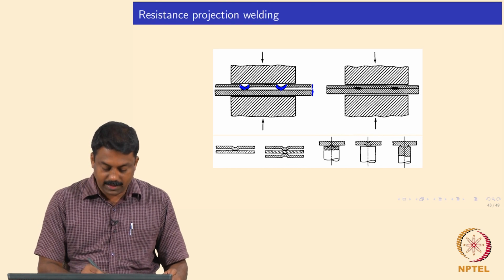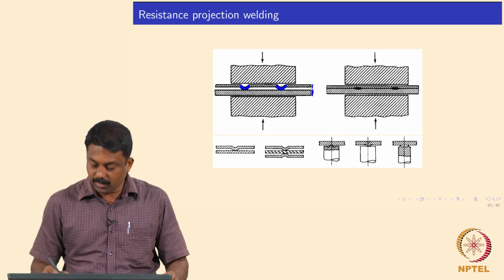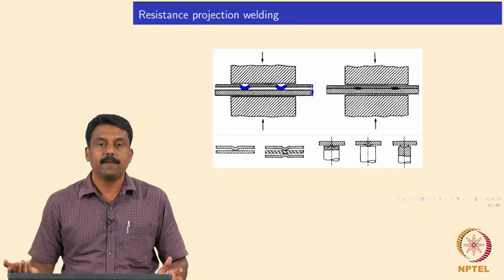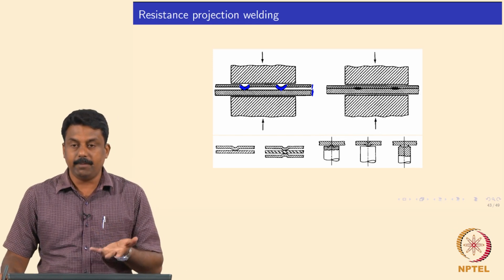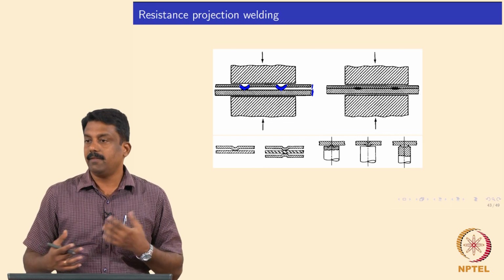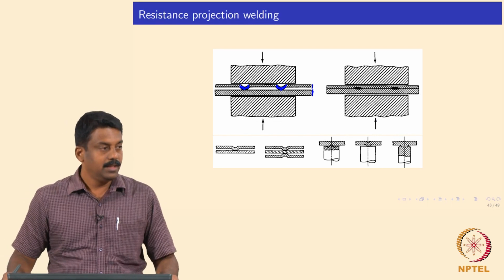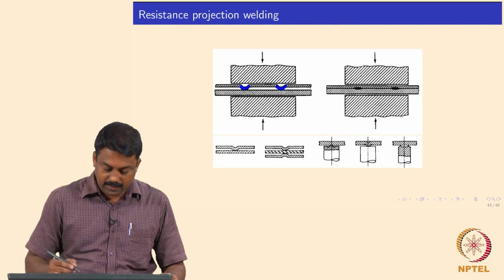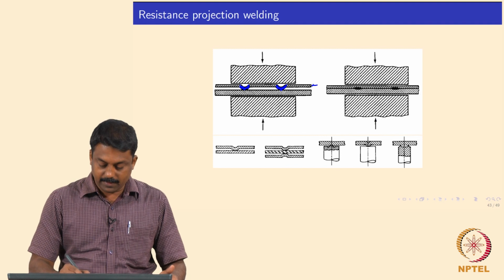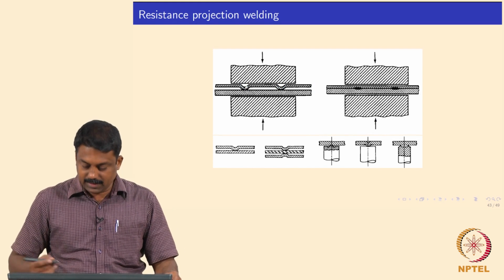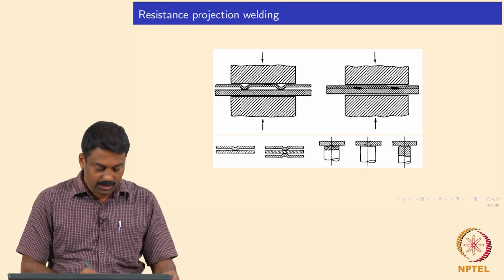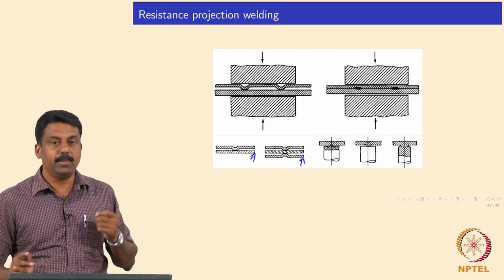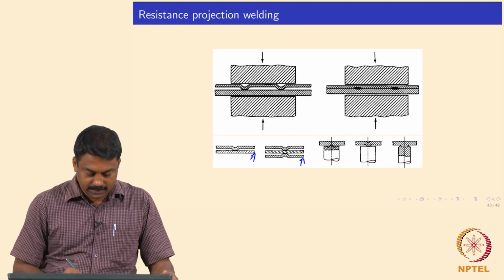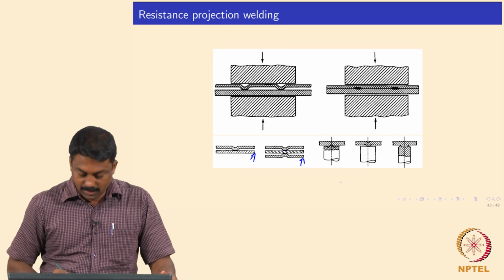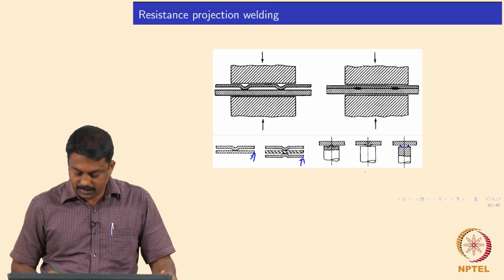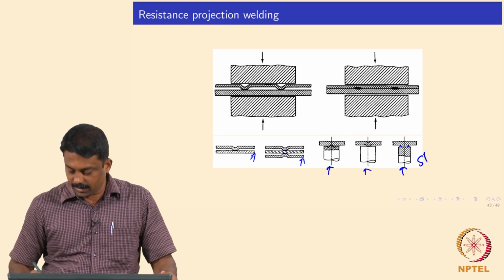So, you can make a heating here and here, and subsequently do a compressive loading at the interface, and this sheet becomes straighter. The advantage is that there is a mechanical deformation which can also aid the weld interface formation. So, projection welding can be used effectively, especially when welding dissimilar thicknesses. This is done in various geometries, for example single sheets, and you can also do multiple sheets to make laminates. You may also have 3 sheets welded together, and you may have some projections, and these are commonly used for welding studs or fasteners.